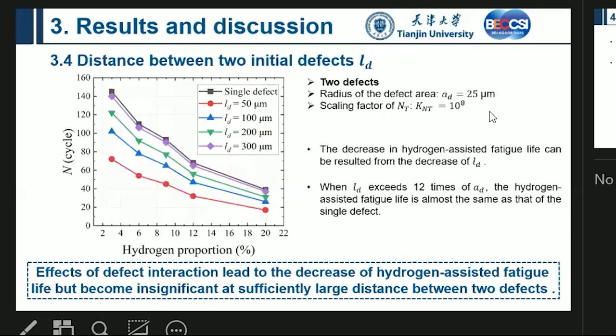Okay, and then we take a look at how the second defect will influence the initial defect. So, for example, the closer, that means the more influence. Here, this one is only 50 micrometers, but this one will be 300 micrometers. So that means very close, actually, very close. More or less like the single defect effect.